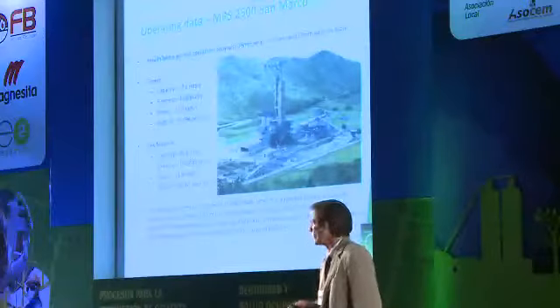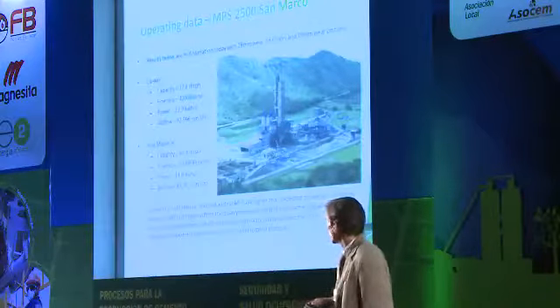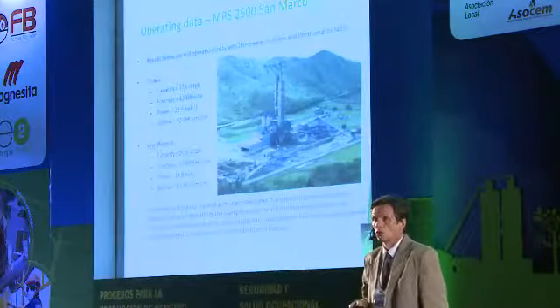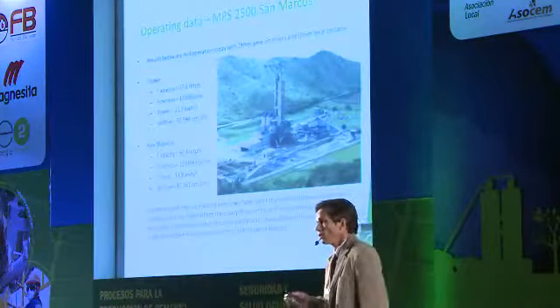Now you look at the figures for the raw material, we're running at 60.4 metric tons per hour with a fineness of 12% on 90 micron, and a reasonably hard raw material, 14.8 kilowatt hours per ton. And interesting, you see the airflow is very close to the clinker at 87,000 normal cubic meters per hour. So again, you see the adjustments between the raw and the clinker are very minimal. It is really hydraulics and classifier. In both the materials, they are somewhat harder than was anticipated, but the mill is still obtaining the required capacities and the guarantees as put out by the client.